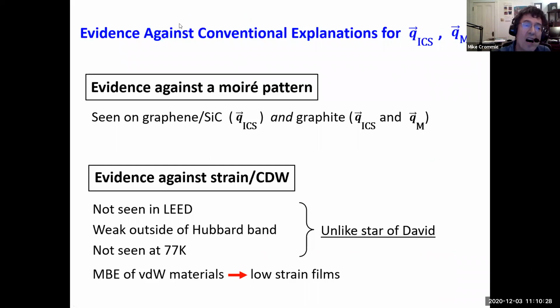So the next obvious thing that you ask yourself is, well, maybe it's a Moire pattern. You know, maybe there's a Moire pattern that we're seeing. Well, it turns out that if you consider all the possible Moire patterns for 1T TaSe2 on top of graphene, then it doesn't work. You don't get the right periodicity. If you do the little twisty trick and calculate the Moire patterns, you don't get the right periodicity.